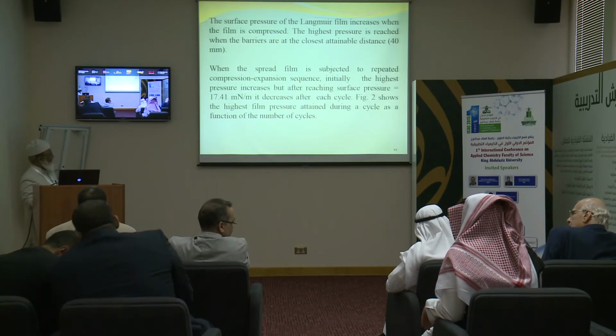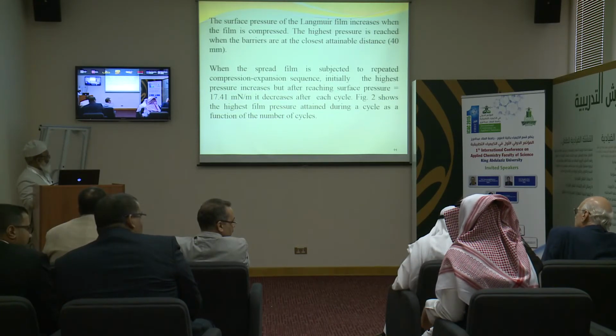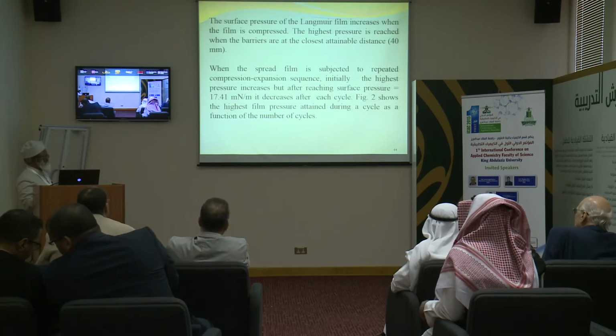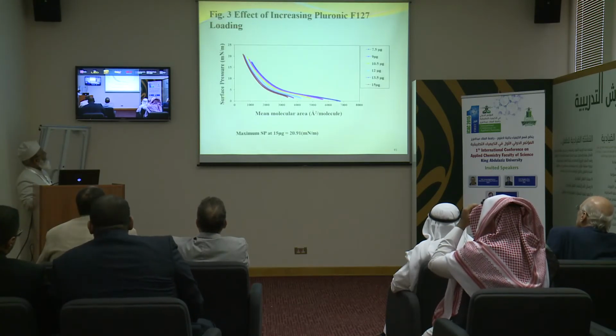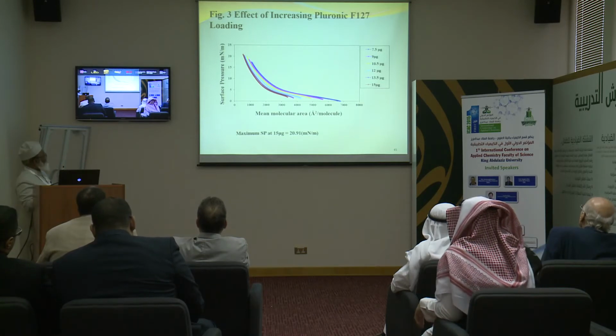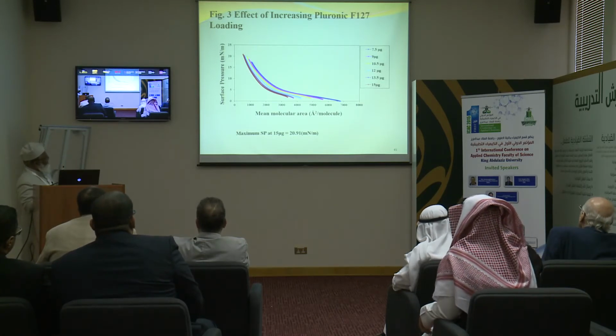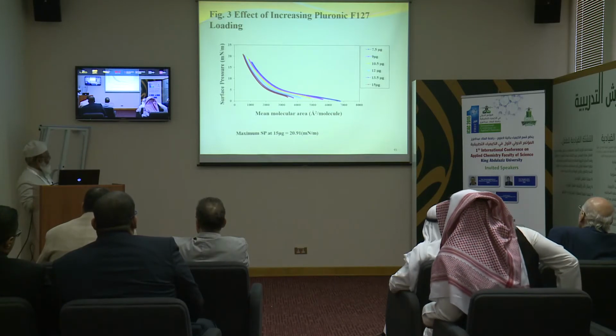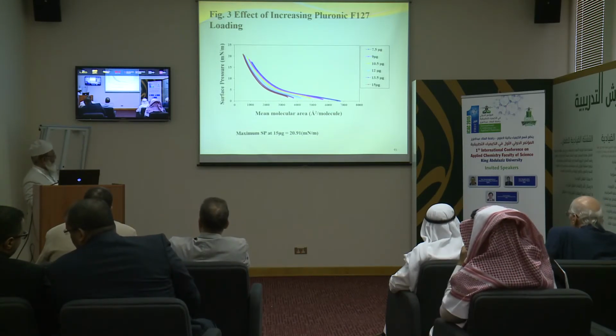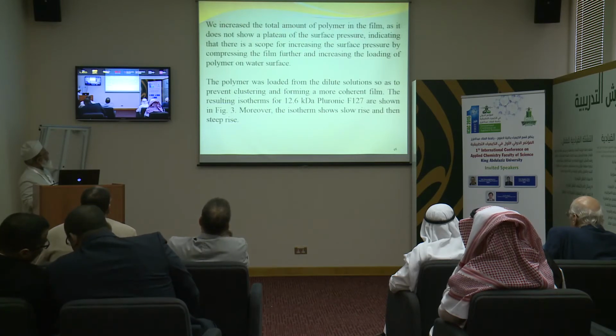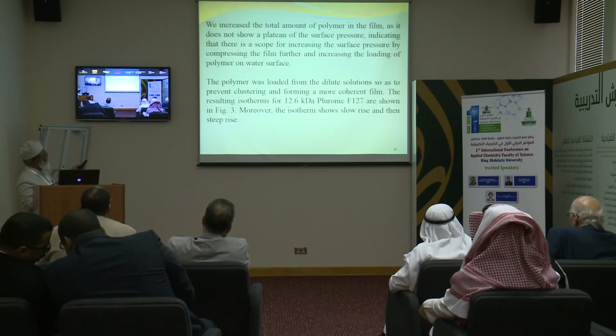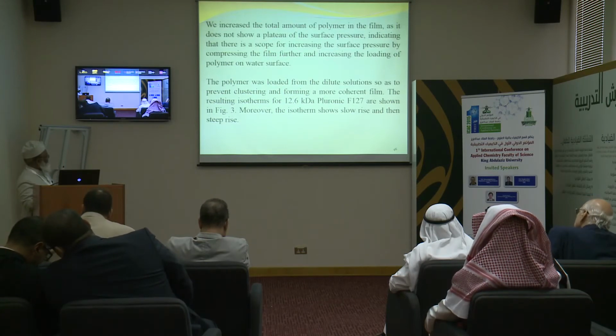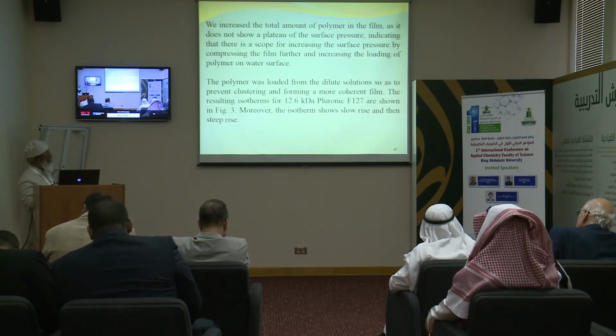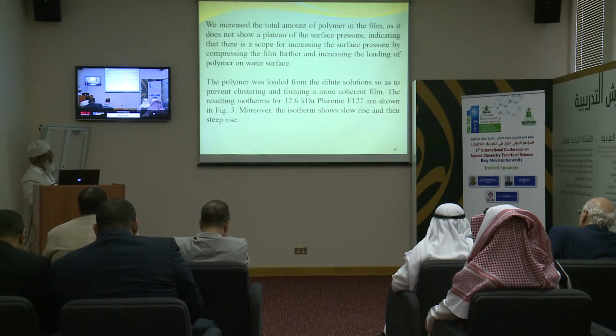It decreases after each cycle, and the figure shows the surface pressure as a function of the number of cycles. The figure shows the effect of increasing the loading of polymer on the stability, from 7.5 microgram to 15 microgram, and the maximum surface pressure was observed as 20.91. Now you see that when we increase the loading from the dilute solution, so as to prevent clustering and form a more coherent film, the resulting isotherm has been shown, and moreover the isotherm shows a slow rise and then a steep rise.